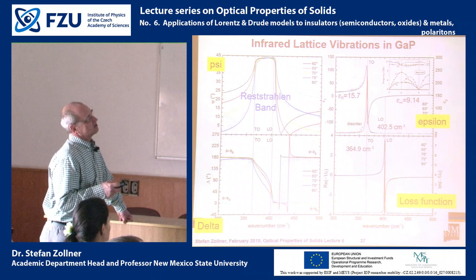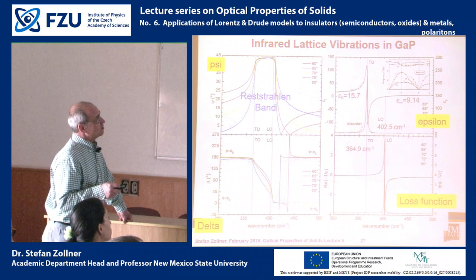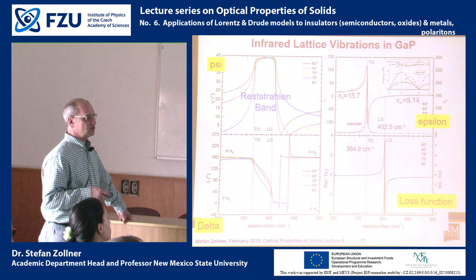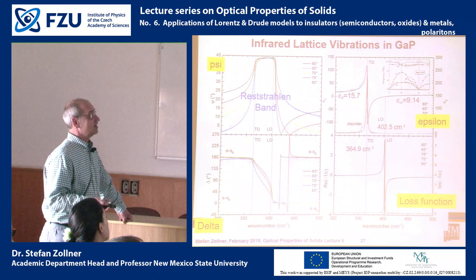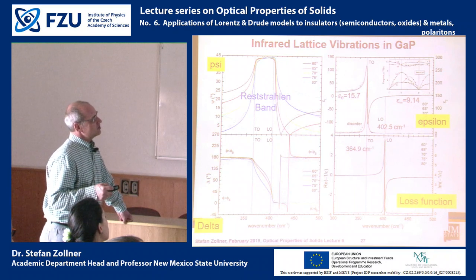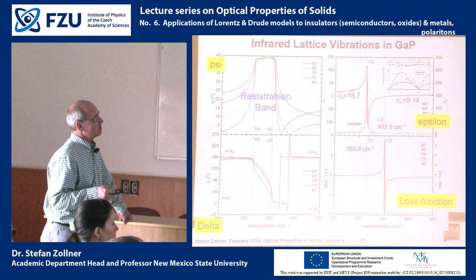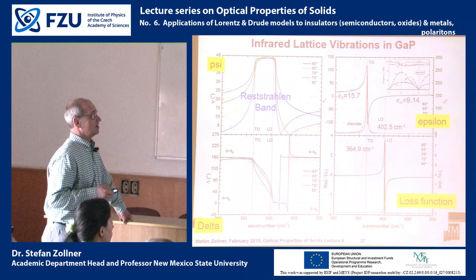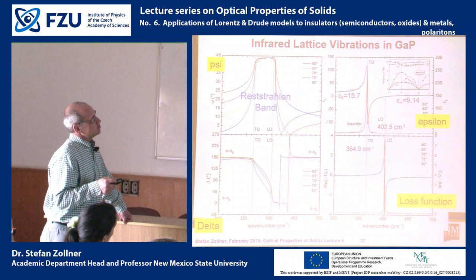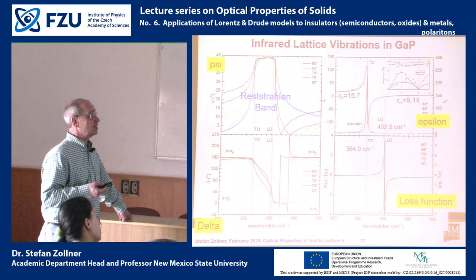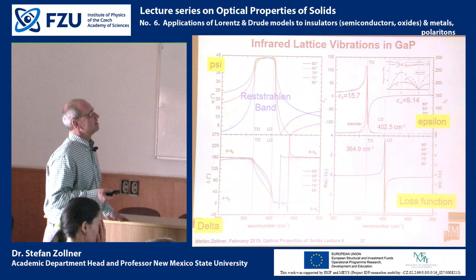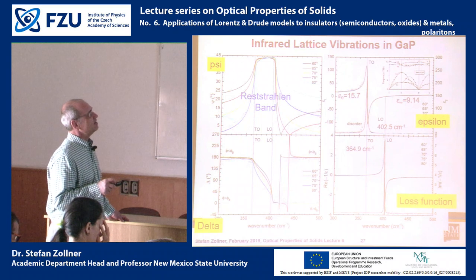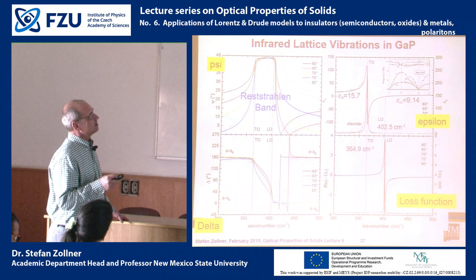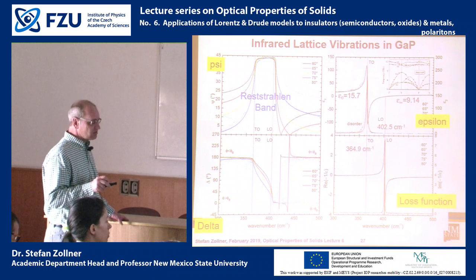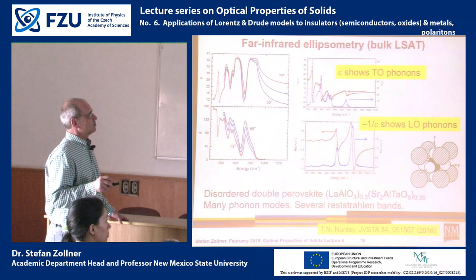In terms of the physics, we could say, well, the longitudinal mode has a higher frequency than the transverse mode, so at higher frequencies things typically decay faster because they can decay into other things. So we would expect that the longitudinal optical mode, because of its larger frequency, should have a larger broadening parameter than the TO mode. And looking at the dispersion relation, the TO and the LO mode will decay into different types of acoustic modes. And again, depending on the microscopic details of these anharmonic decay processes, that might explain why there should be different broadening parameters for the TO and the LO mode.